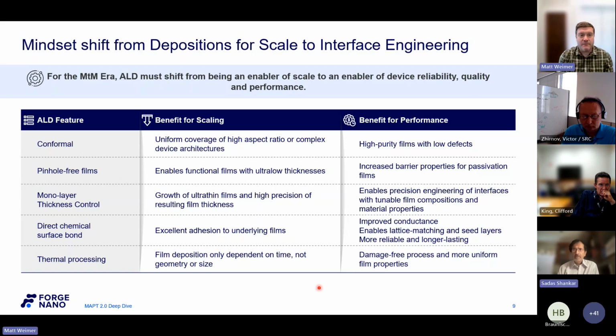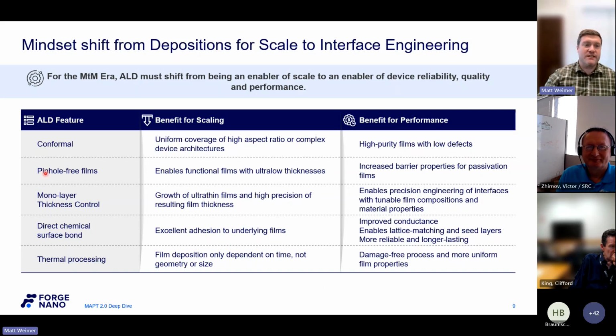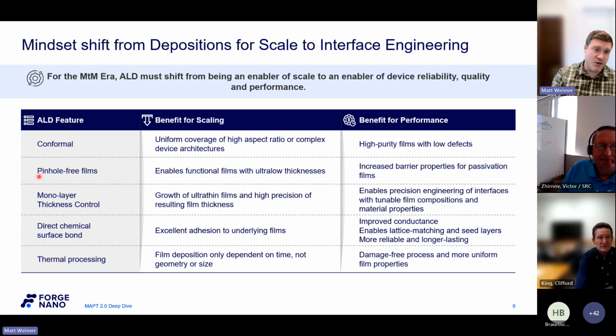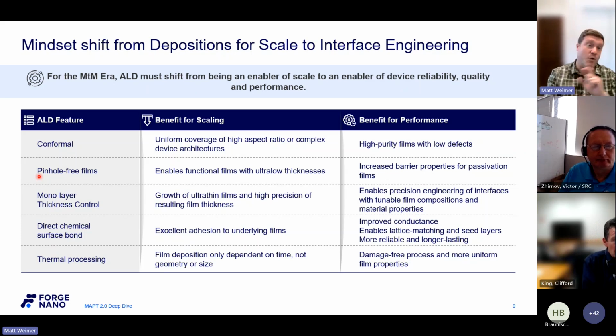Thank you. Okay, so maybe looks like we're good for questions. I've already talked about the conformality nature. One thing that I haven't noticed, but it is quite important, is you get a uniform pinhole-free film at a very thin total thickness. And again, to Alan's point, in the ideal situation, right? So typically with oxides, we're talking within a nanometer or few. Now, if you talk about metals, there are other things at play here. So again, this is quite dependent. But normally, if you think about why Intel adopted hafnium oxide as a high-K dielectric, it was because you got a uniform film without pinholes at quite thin total thickness. So that is, typically speaking, one of the benefits of ALD.